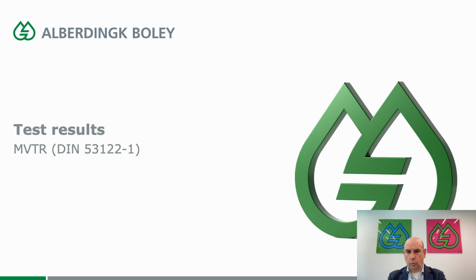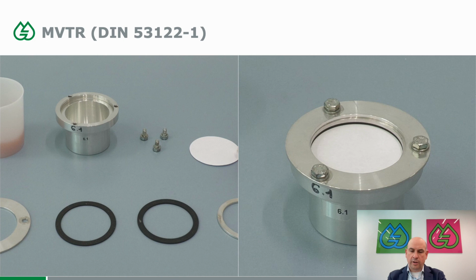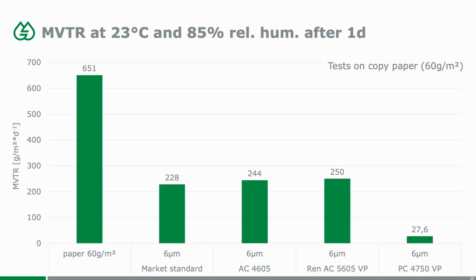Then we're getting to one of the most important parameters for true barrier coatings, and that's the MVTR. The MVTR in our case is measured in cups according to DIN 53122/1. It's a wet cup method. So here you can see the moisture vapor transmission rate at 23 degrees centigrade and 85% relative humidity after 1 day. And you've noticed I've had to switch off my video because otherwise you will not be able to see all test results. So the paper on its own is a very poor barrier, as you can see, with 651 gram per square meter per day.